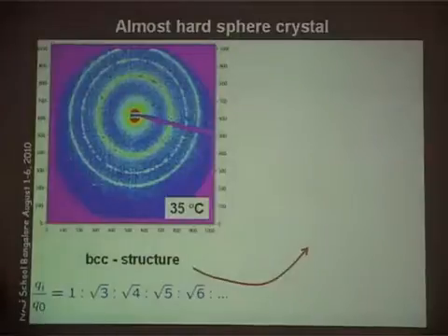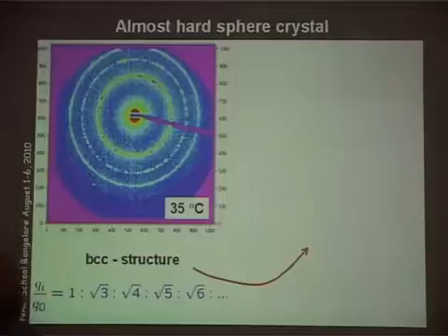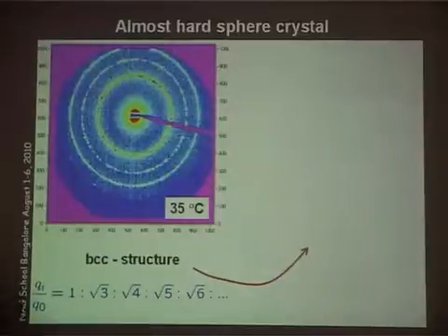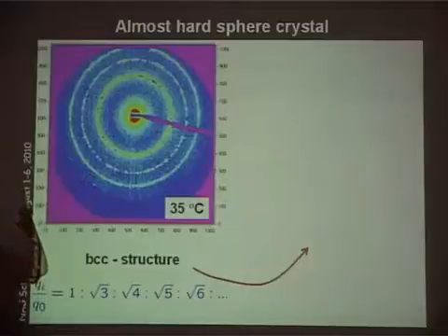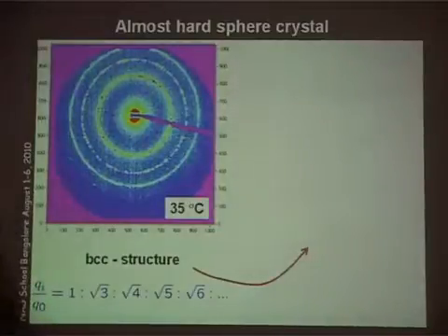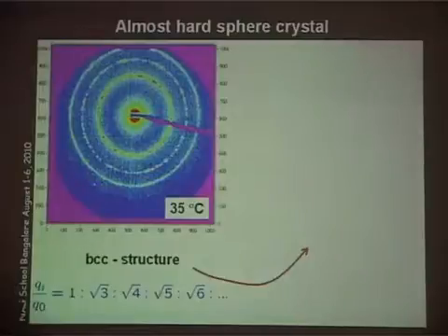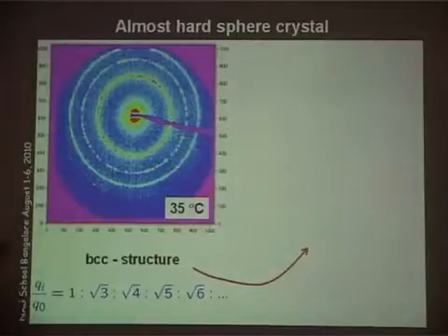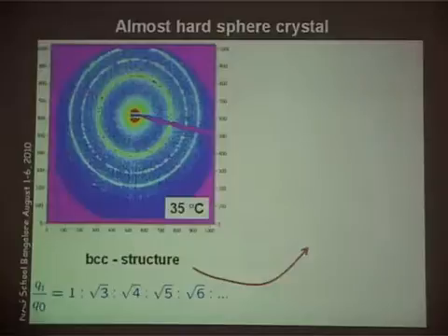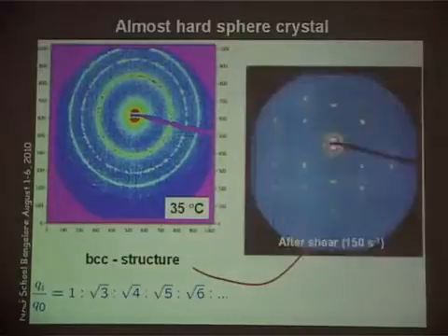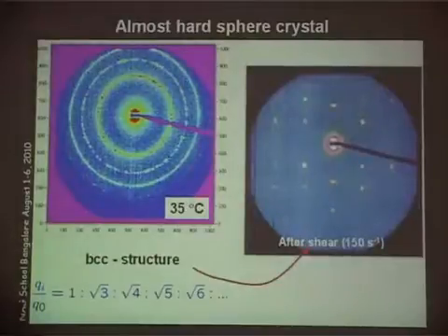Now you can play a lot with that, because we heard from Surajit yesterday about martensite. These are BCC crystals, only on a very different scale. Because the building units are now 10 or 50 times larger, I have a much lower strength. They are much softer. The larger the building units, the lower the elastic modulus of your system is. So what we can do is shear it, and when we shear it sufficiently long, we actually get a single crystal over many centimeters of micelles.